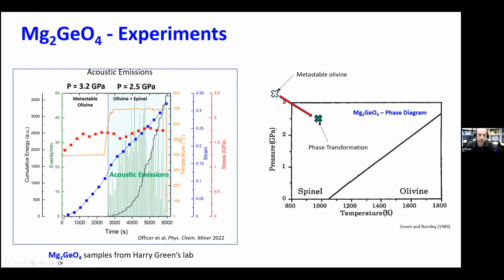And then the strain: at this point, it's unstrained. We haven't started deforming it yet. But then we start deforming it and the strain starts to increase at 400 degrees Celsius. You can see that the differential stress on the sample is also increasing. But what you don't see here is any acoustic emissions, because the temperature is too low. We haven't initiated the transformation. We're up here on this phase diagram, which doesn't go that far, and we just have metastable olivine, no transformation, no acoustic activity.